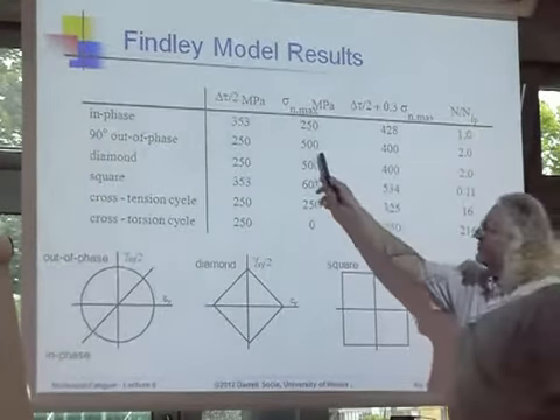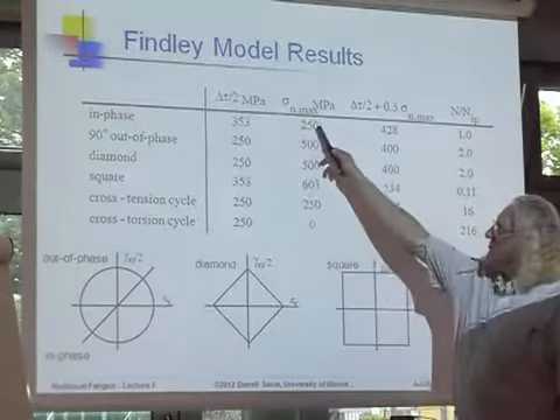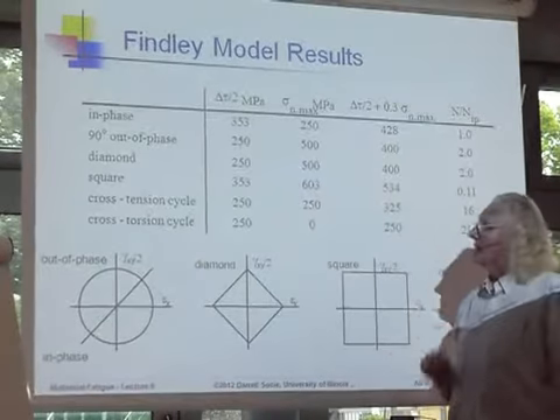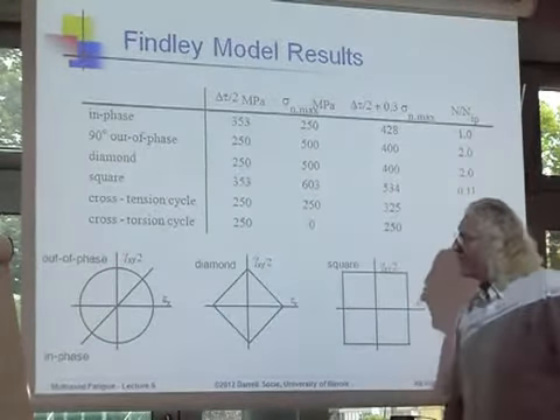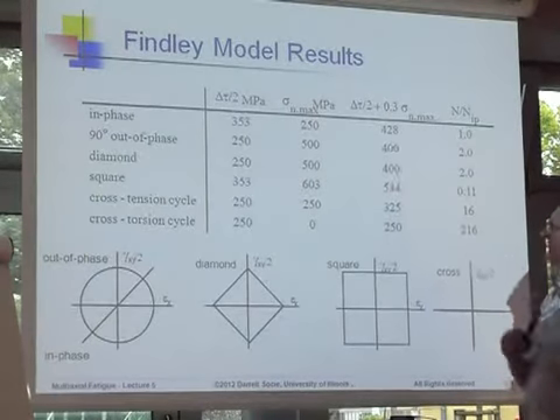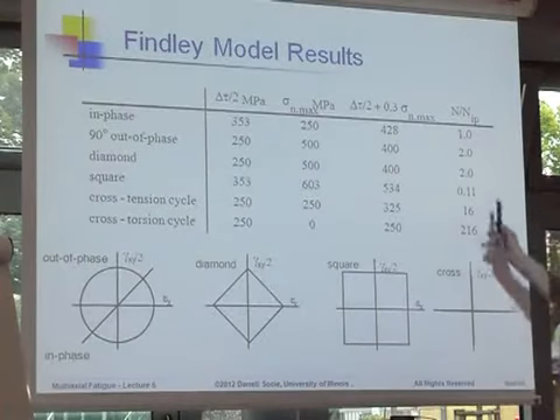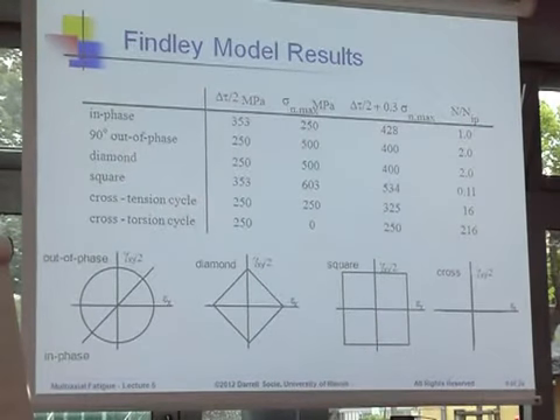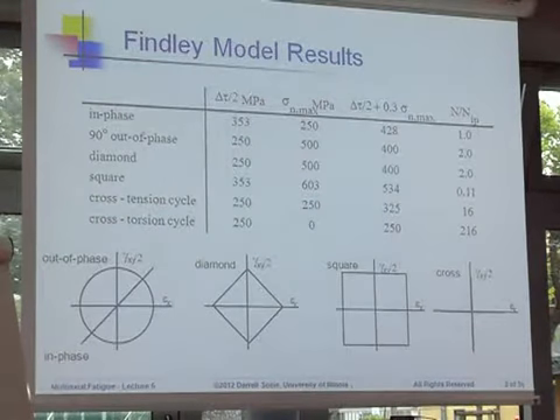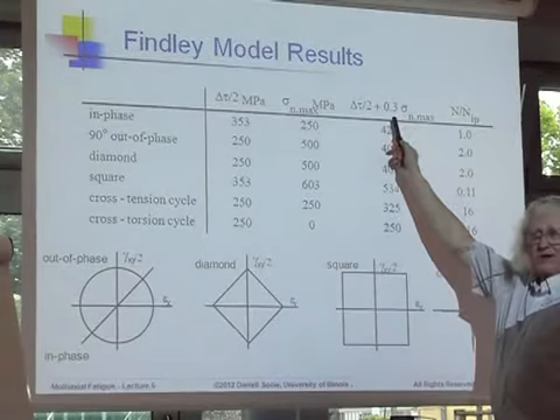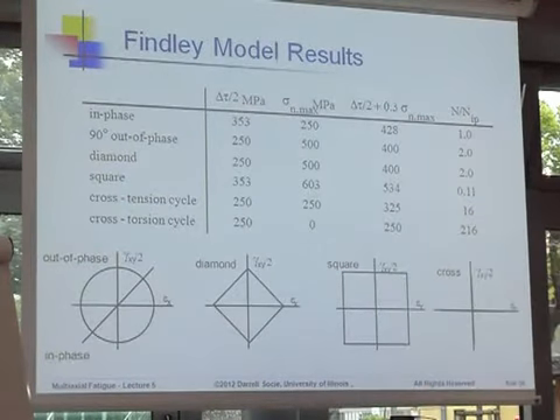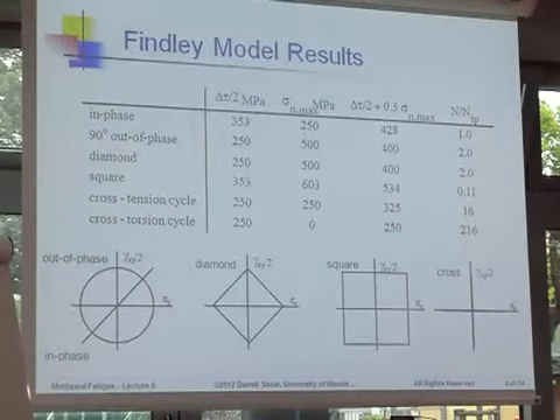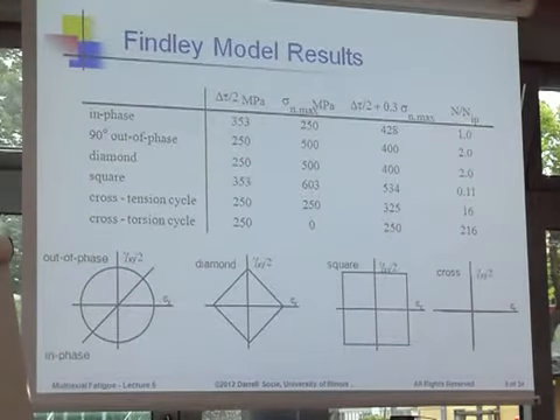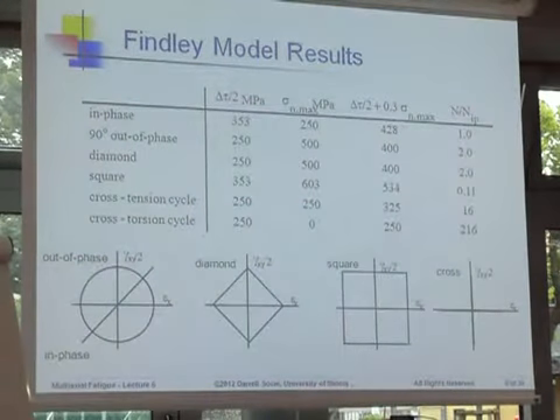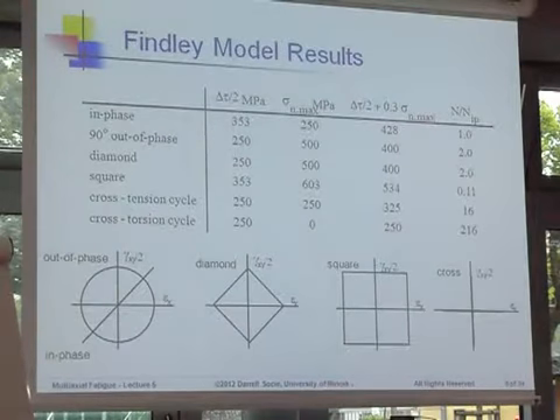And sure enough, you can see that the normal stress for this path is twice as high. So this is a little bit lower, this is twice as large, and if I look at Findley's criteria, it turns out to be here, and not very different. Lifetime said maybe twice, 2 times in the lifetime. If I wanted to make them the same, maybe I could adjust this constant a little bit, make it a little bit less or a little bit more, but basically the same. Who would ever guess this? And the answer is no. So the only way to think about interface loading is to do the calculations, because none of us can think about how the shear and the normal terms combine.